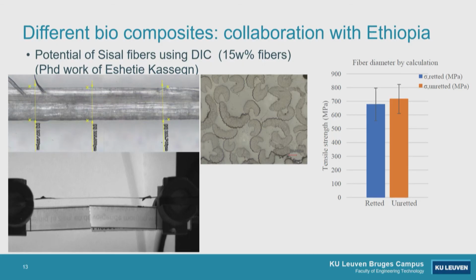Okay, if we look at, let's say, these sisal fibers used to reinforce our PLA, then at first some measurements were done on the strength of these fibers. And this has been done using DIC in the research group of Aart van Vuure in Leuven. So they did single fiber testing and had a look at the potential of this type of fiber. So that's the PhD work of Eshetie Kassegn. And only results are there for 15% of fibers. We also have to deal with a completely different cross-section of the fibers. It's kind of C-shape, and also the diameters are quite large, so it's more rough fibers.